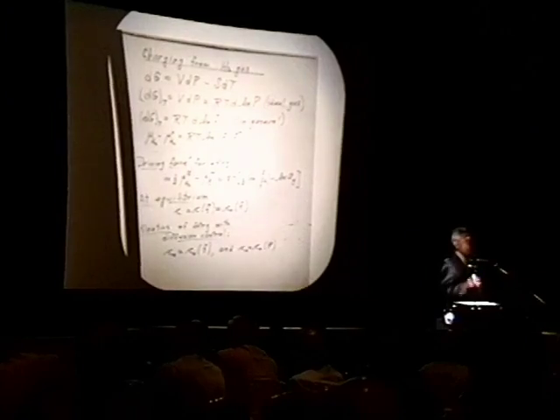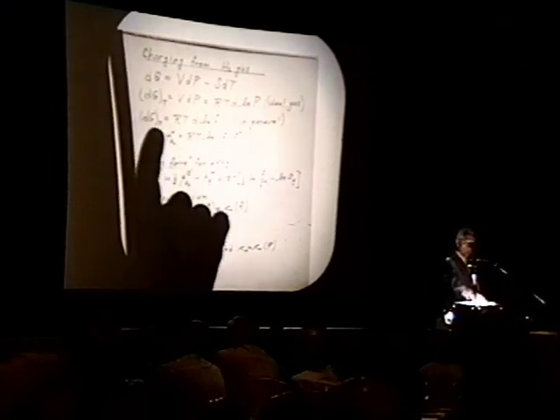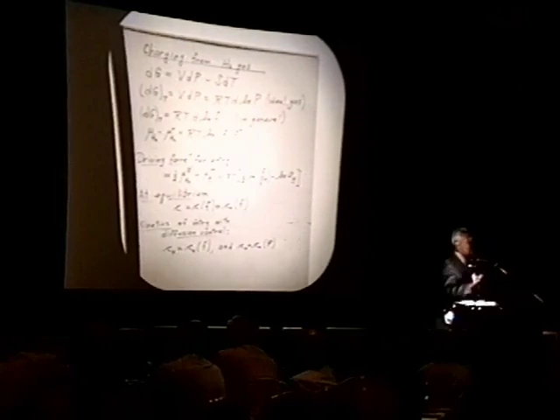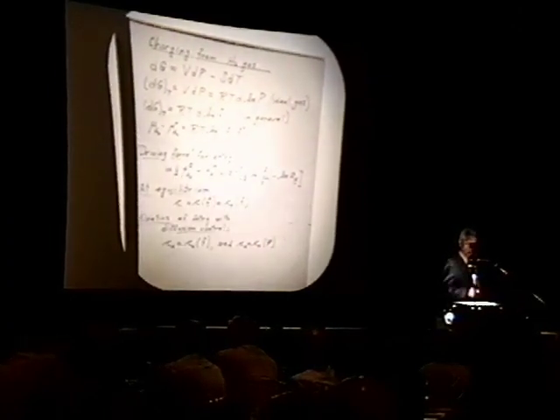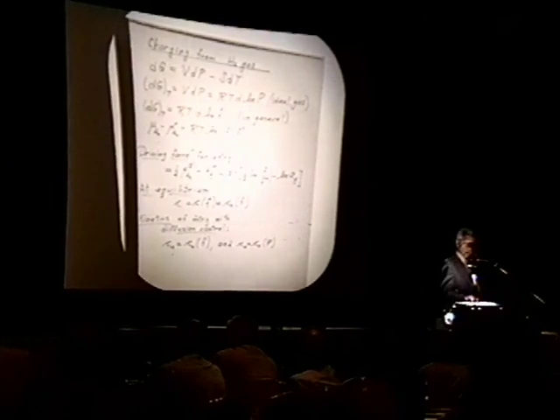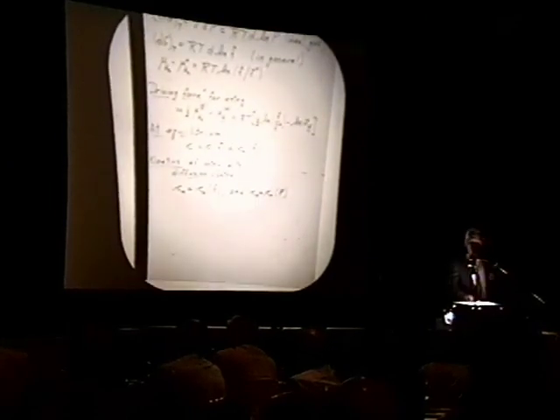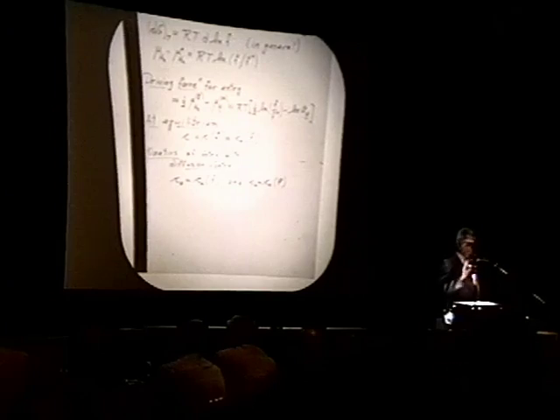In order to have the same formalism for a non-ideal gas, which hydrogen at high pressure is, people have used this formulation where now f is called fugacity. So that's a very general expression. Changes in fugacity, therefore, are the measure of the work at constant temperature that a gas can do. The chemical potential of the hydrogen molecule gas phase is therefore given with respect to a reference state by this expression, with the ratio of the fugacity in the existing situation divided by the fugacity of the standard reference state.